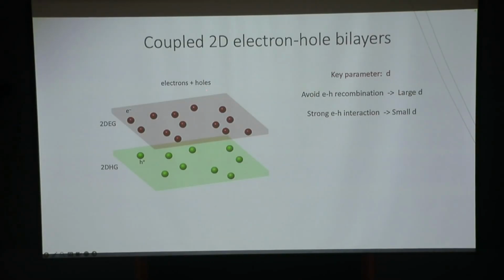In this kind of system, of course, one of the key parameters is the separation between these two layers. You want it to be large enough so that the electron and hole tunneling are really suppressed, so they live for a very long time. But at the same time, you want it to be very small, because you want the electron-hole interaction to remain very strong, and it can compete effectively with the repulsive Coulomb interactions.